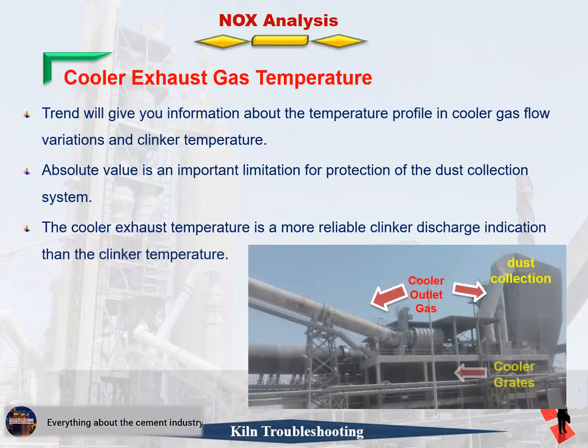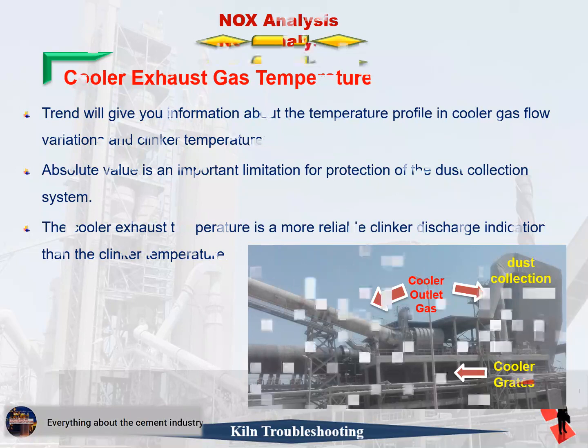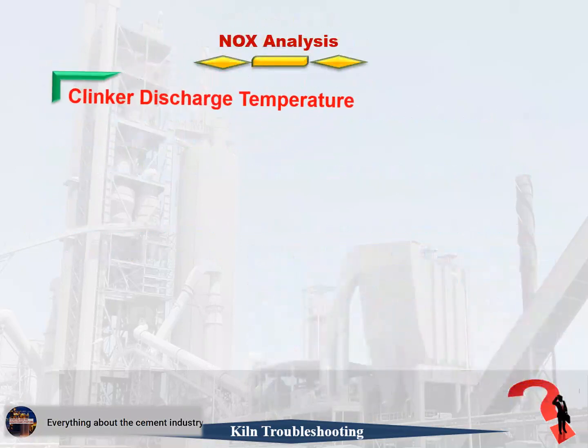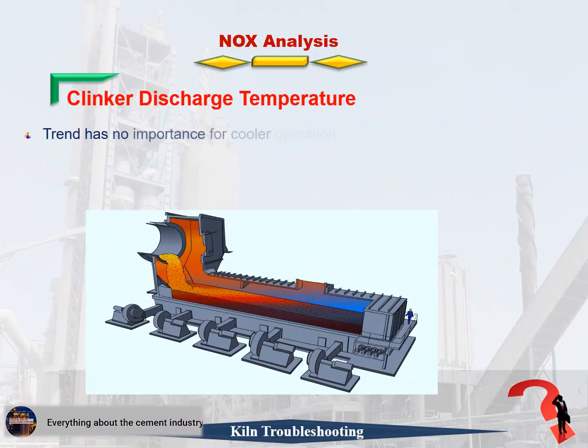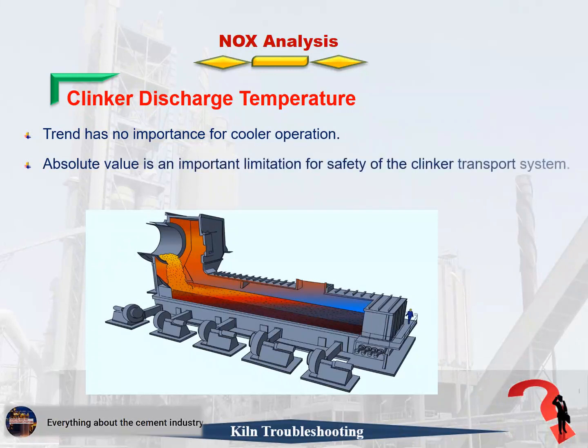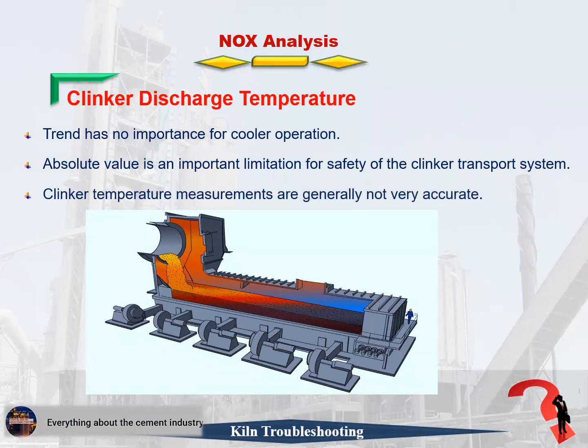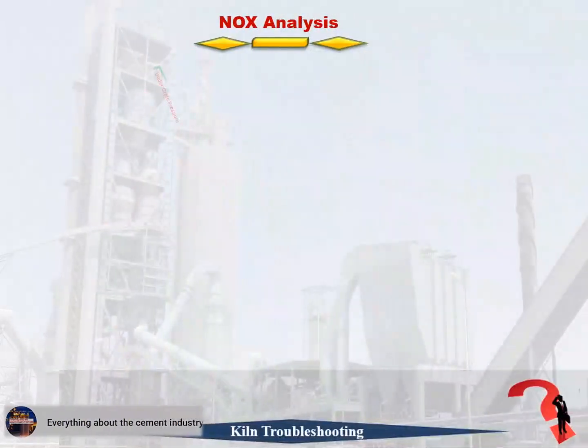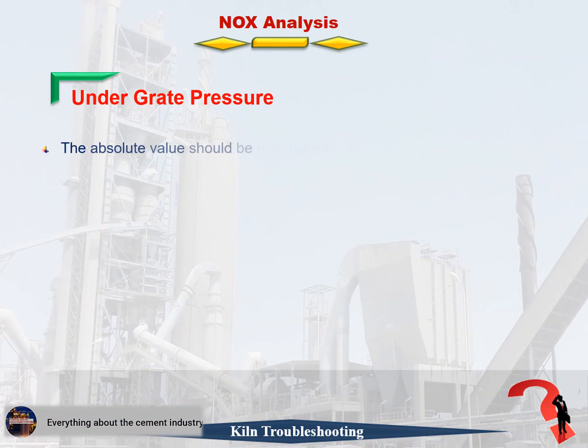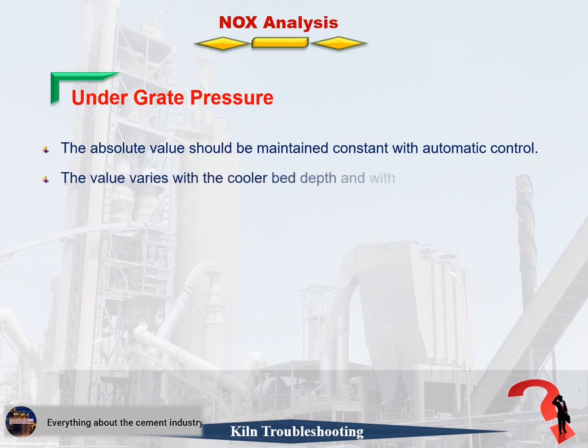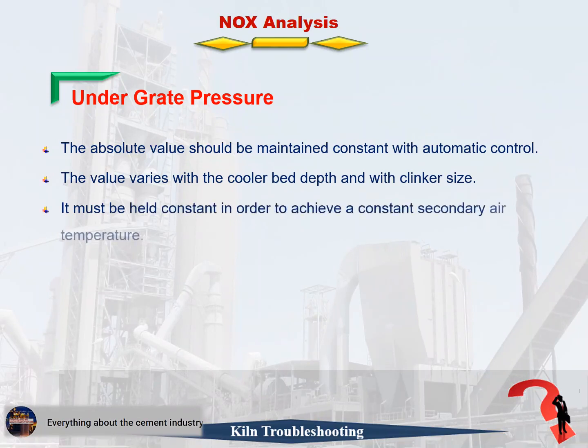This picture shows the exit of gases from the cooler, in addition to the secondary gases entering the kiln. Clinker discharge temperature. Trend has no importance for cooler operation. Absolute value is an important limitation for safety of the clinker transport system. Clinker temperature measurements are generally not very accurate. Under grate pressure: the absolute value should be maintained constant with automatic control. The value varies with the cooler bed depth and with clinker size. It must be held constant in order to achieve a constant secondary air temperature.